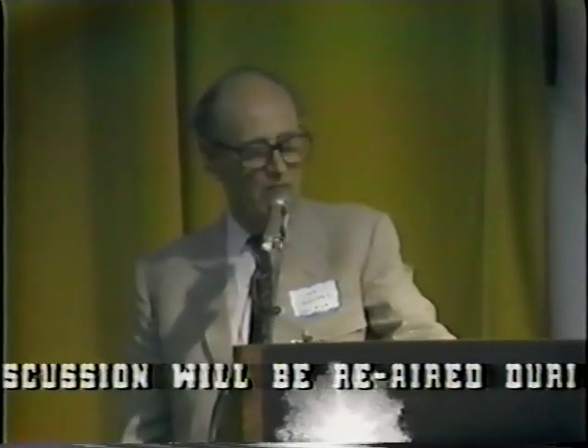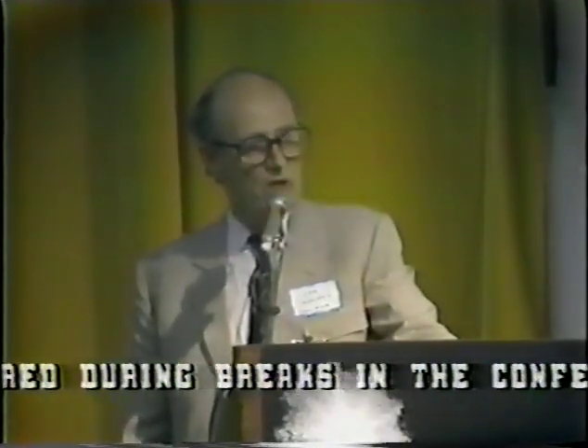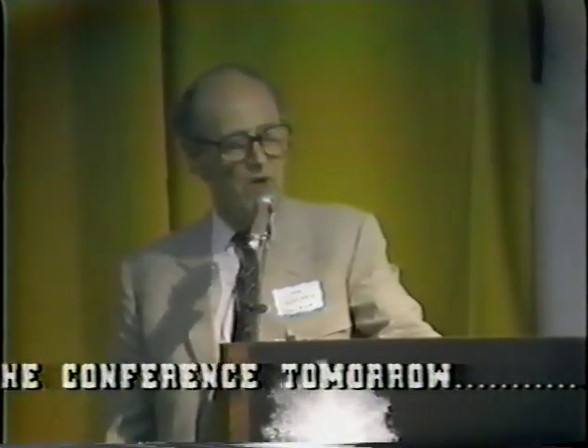I'd like to make an electrochemical comment on that. That is true enough. The relationship between permeation, theta, the occupancy on the surface, and the poison is quite complicated. Most of the work that's known about this is for iron, and what I'm going to say is about hydrogen on iron and not deuterium on palladium, but I suspect they're rather related. Whether you increase the rate of going in and the final rate inside is very much a balance, because you affect the equilibrium constant between the inside and the outside, but at the same time you affect the kinetics of the reaction on the surface. But what you may probably do with many poisons is increase the overpotential rather than the H inside. And because of those mysterious equations that I briefly presented right at the beginning, that may have very profound effects. Yes?